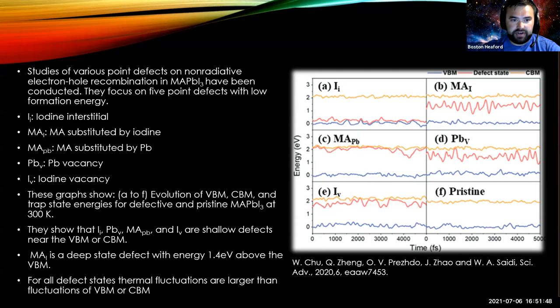And you can see on these graphs, some of them are pretty intuitive that they'd be a shallow state or a deep state defect. So for example, the iodine interstitial is a shallow state, as well as those other three listed, the lead vacancy, the methyl ammonium substitution, and the iodine vacancy. Methyl ammonium substituted by iodine is a deep state defect with an energy 1.4 electron volts above the valence band maximum.